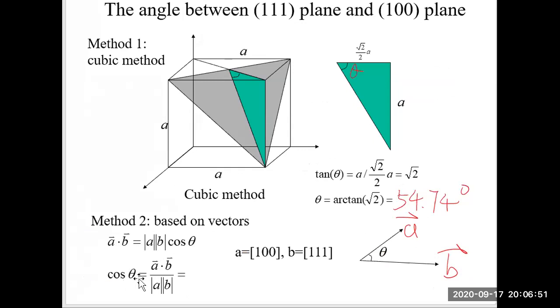So cosine theta will be equal to A dot B divided by the length of A and the length of B. Then theta can be calculated by arc cosine. In our case, we want to calculate the angle between the 111 plane and the 100 plane. Vector A is 100, which is perpendicular to the 100 plane, and vector B is 111, which is perpendicular to the 111 plane.